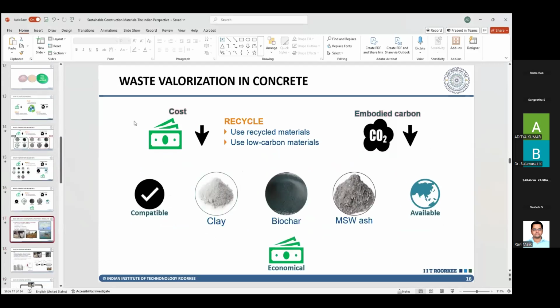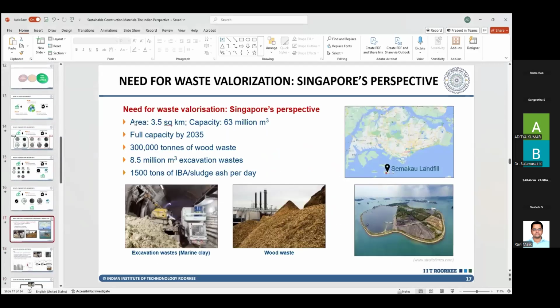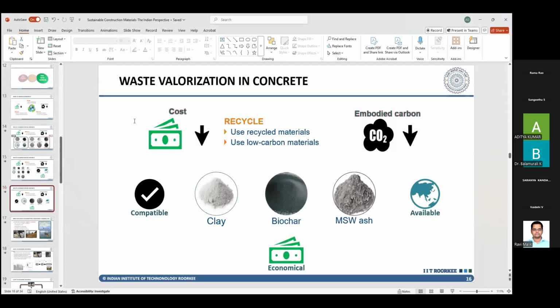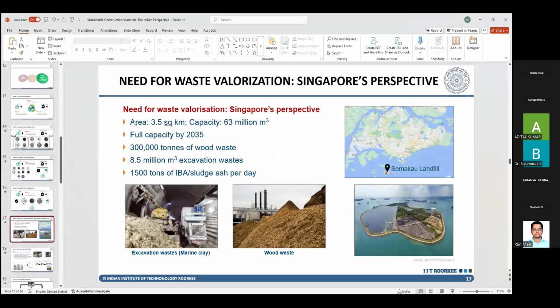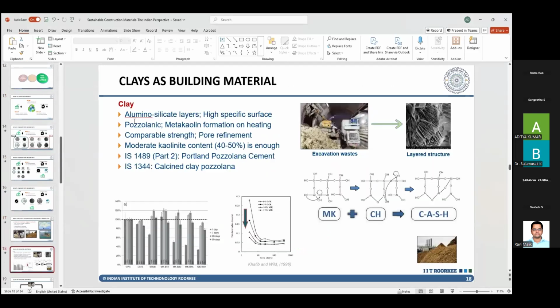So this is again the compatibility, the availability, and economics issue. And the landfill I was talking about in Singapore, where they're dumping all their ash. So kaolinite is a naturally occurring mineral in clay. What it does is, if you heat that clay, if you heat the kaolinite to 600 or higher temperatures, there is atomic restructuring that occurs at that temperature. And if done right, you are able to obtain a different structure, like this. And this structure is called metakaolin.